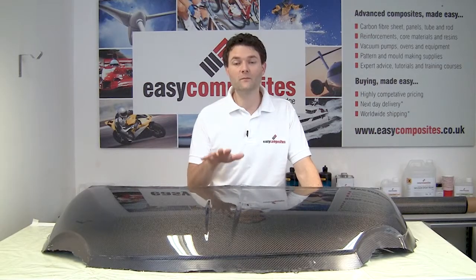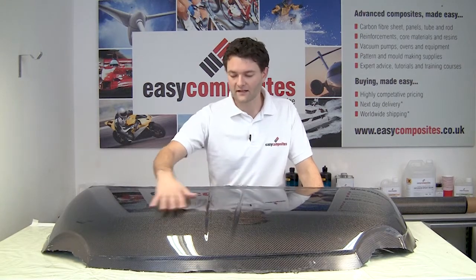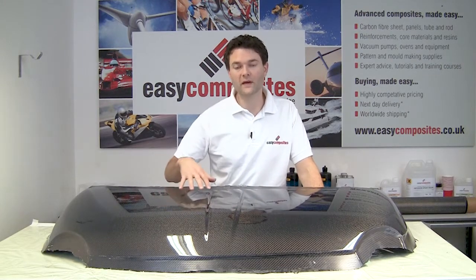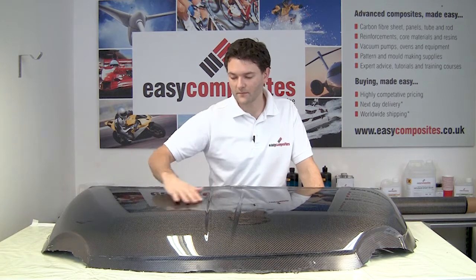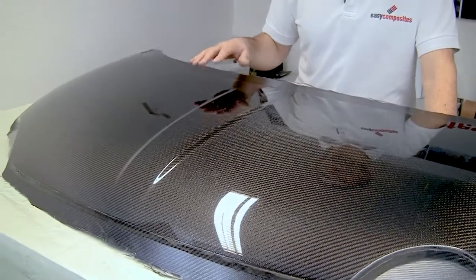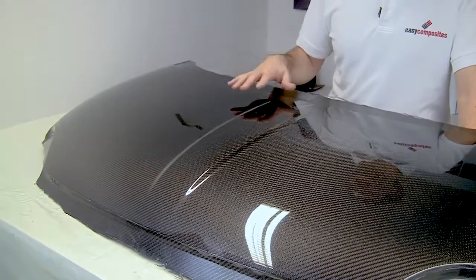With this part out of the mould, you can really see all of this hard work's paid off. We've got a fantastic mirror gloss over the surface of the bonnet from that clear gel coat that we've used. There's no pinholes whatsoever, there's no bubbles, there's no air inclusions, and so you've got to be pretty pleased with that at this stage.